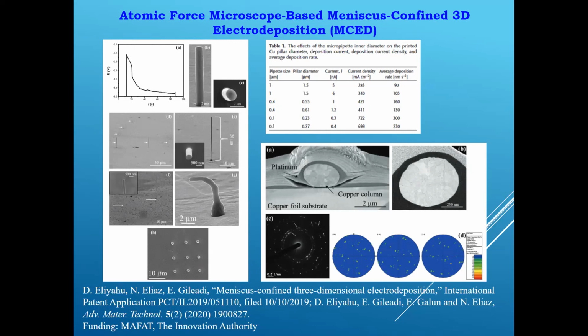We calculated yield strength of copper of 370 to 537 megapascal, respectively, for 1.5 micron and 500 nanometer pillars. This is much higher than pure copper, the C11000, or even previous copper with some micron grains.